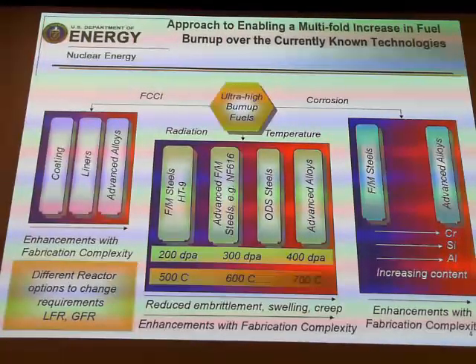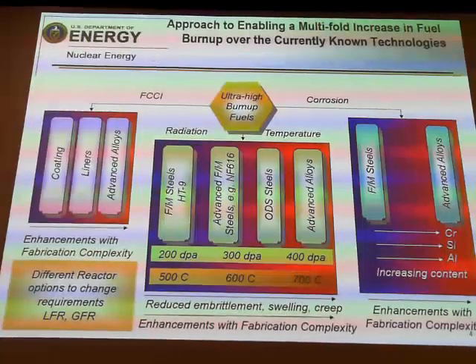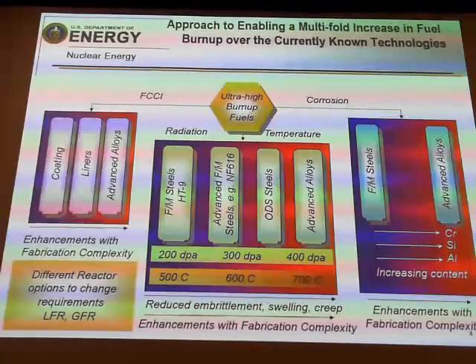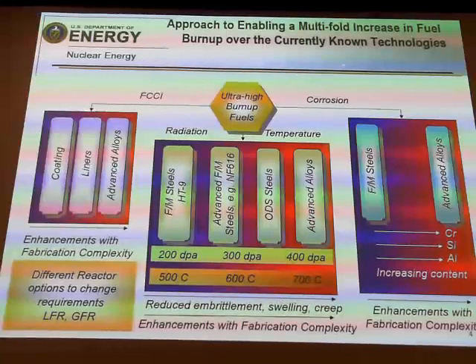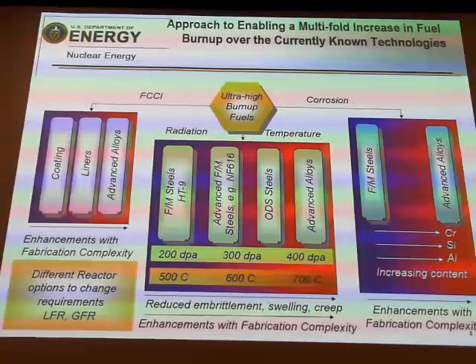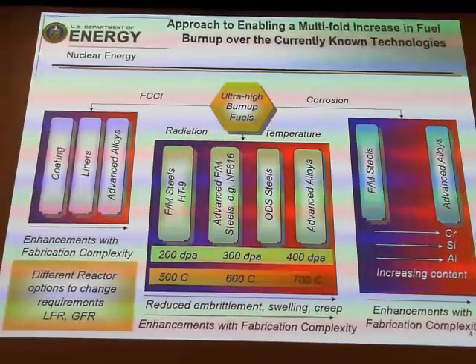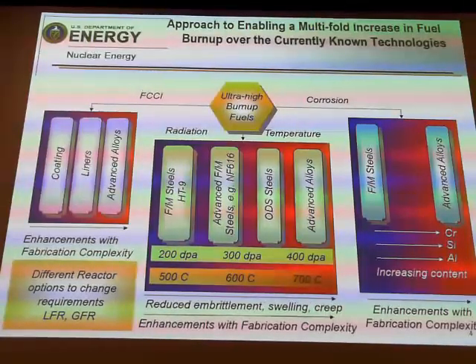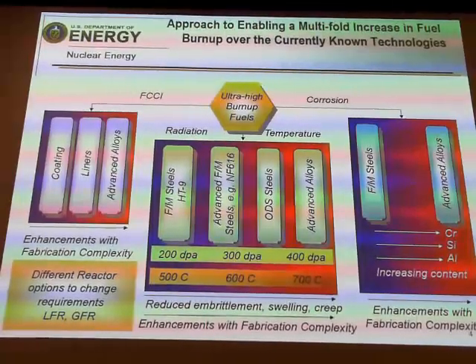But the main aim there is to enable a multifold increase in fuel burnup over the currently known technology. So we know that we can push HT9, we can push ferritic martensitic steels to fairly high doses, even out to about 200 dPa. But for the ultra-high burnup fuels, we'd like to push the burnup to 30 to 40% burnup, which means the dose in the cladding could be out to 300 to 400 dPa. So it's really a grand challenge to get out there. And in order to do that, there's a lot of things we'll have to overcome.